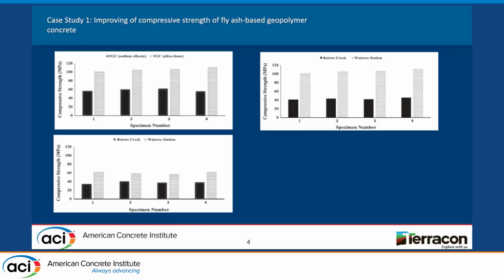We did some extra study to see why we have such an effect. We found out the Waterree Station fly ash has a finer particle size distribution, which means more surface area ready for the reaction.